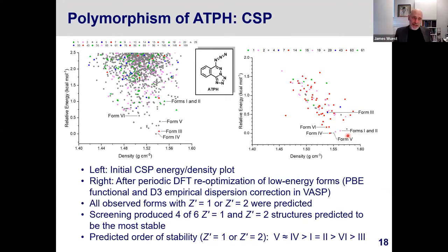So what this means is that the crystal structure prediction is good, and the experimentalists doing the search for the different polymorphic forms are good too. So everything seems to match quite well. The predicted order of stability places form 5 and form 4 very close together. Now, you would not necessarily be reassured that you have identified the global minimum from this, but theory says that they should be very close together.